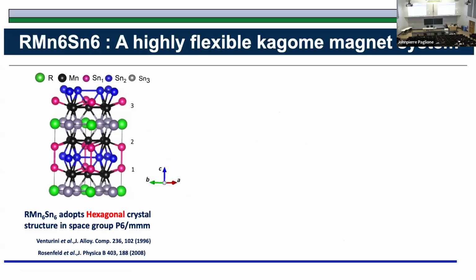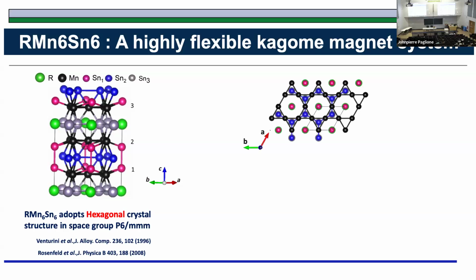So this is called the RMn6Sn6 system. R is a rare earth element, and Mn is manganese. The black atoms are the manganese atoms. The green atoms are the R atoms. And the other 3 different colors are tin atoms, because they sit in 3 inequivalent crystallographic sites, so they are principally different tin atoms. And these manganese atoms form a Kagome lattice in it. So it has a Kagome feature in it.